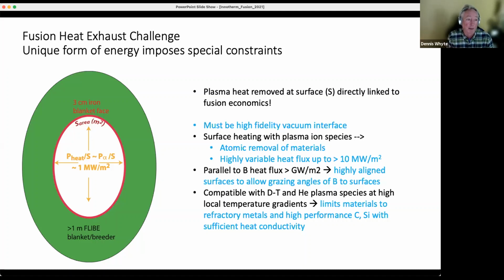And then it also has to be compatible with this rather weird set of fuels, which is hydrogenic fuels and helium. And with establishing very high local temperature gradients, because even with the highest thermal gradient species that we have, you're talking about hundreds of Kelvin per millimeter of thermal gradients in this upper surface. And you've got this corrosive and weirdly interacting hydrogen and helium species with it. So basically this eliminates most engineering materials almost immediately from consideration. We almost always look at refractory metals and things like silicon carbide.